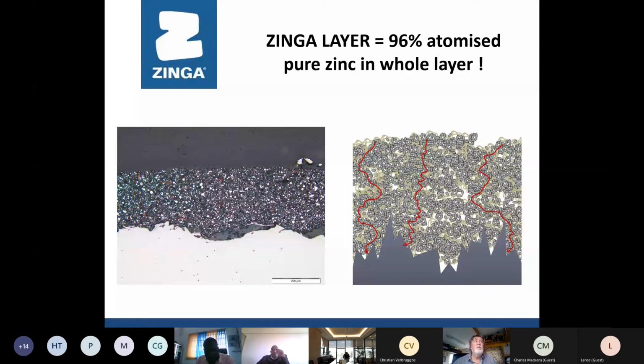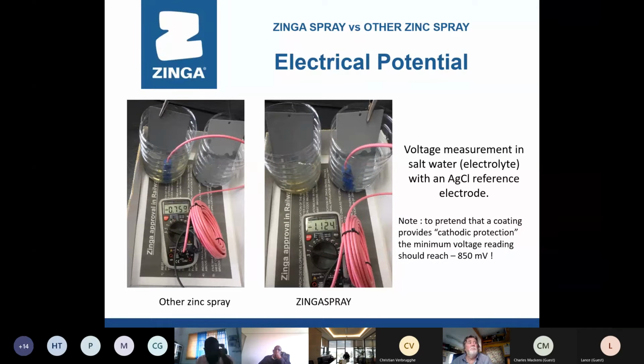And again, we have 96% of atomized zinc, so the entire layer is full of zinc. There's no gaps in between like you get with zinc paints. Here is a test we do to show people. We have architects and engineers who cannot believe that Zinga can produce such a high voltage. On the left, you'll see a zinc paint panel, and they're measuring it with a voltmeter using a silver chloride half cell, and you're getting 759 millivolts. When you look at the Zinga test panel, it's 1,124 millivolts. That's how much voltage is flowing from the Zinga into the steel. And for those of you who've done any work on boats or buried pipelines, the voltage from Zinga is higher than the voltage from aluminium anodes. It's the only coating in the world that can do this.